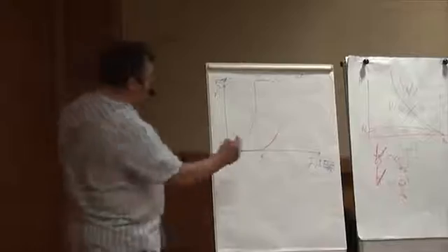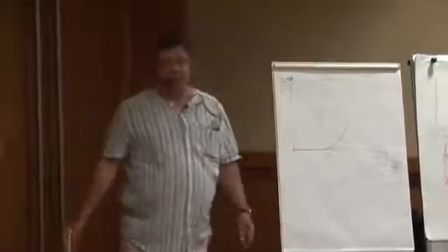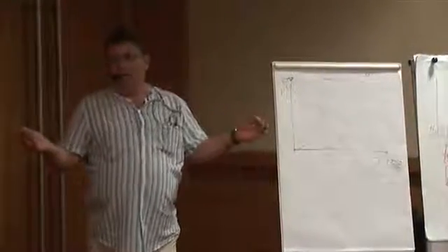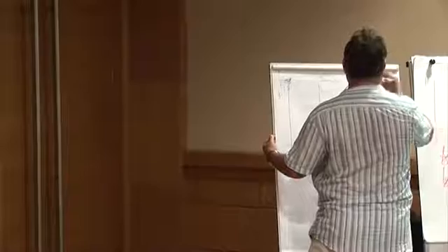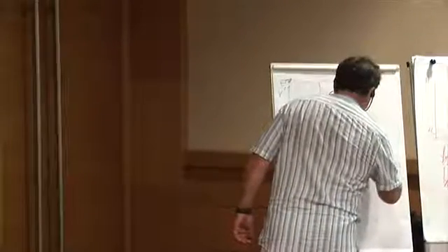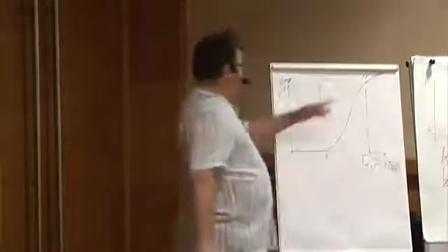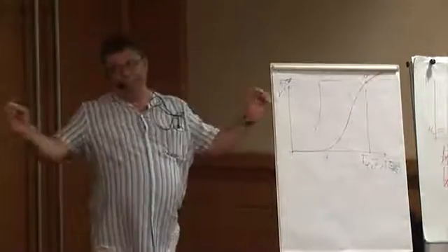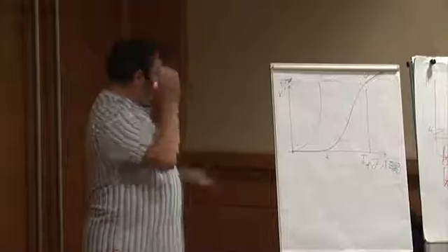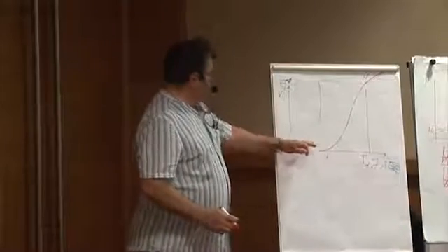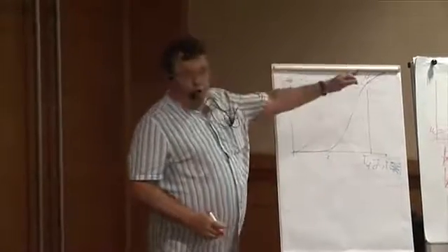What will be happening further? Will it go like a semiconductor? Yes or no? No. It will go like this. It will join the normal one here. And here is the depairing critical current. Here is the current which will break the Cooper pairs apart. So this is the normal, linear scale. In a logarithmic scale, you will see something like this.